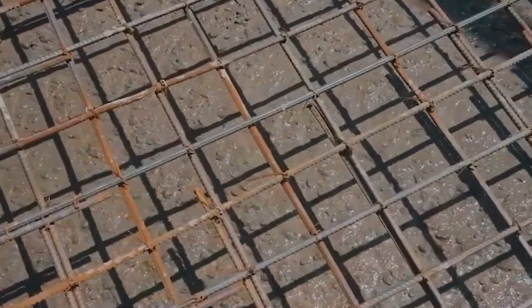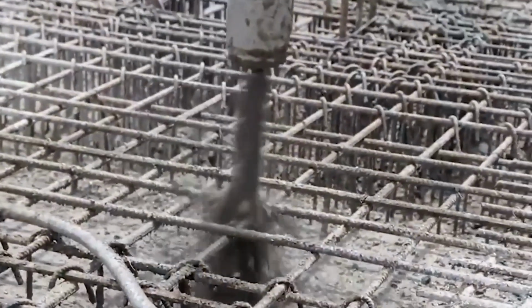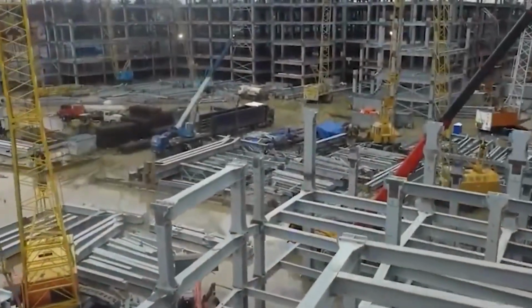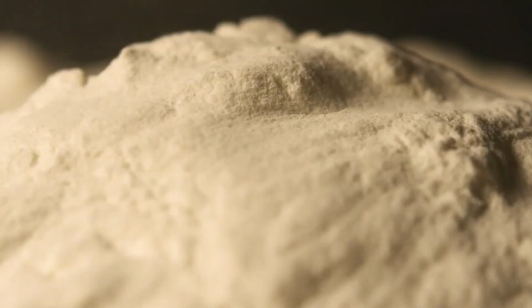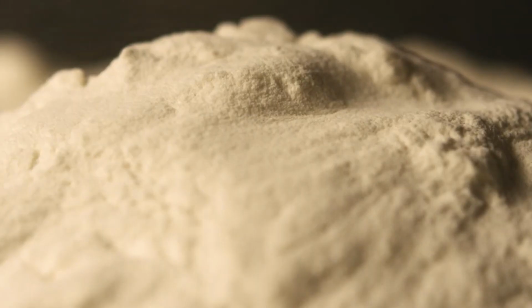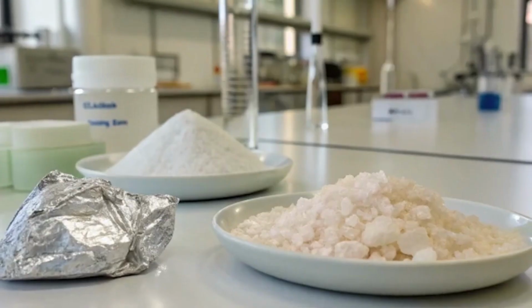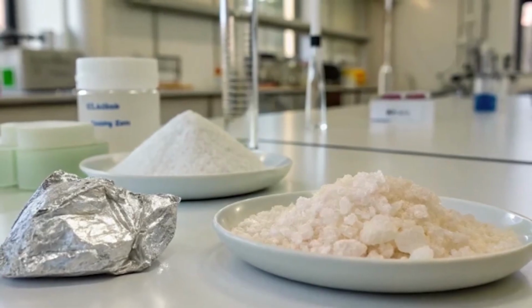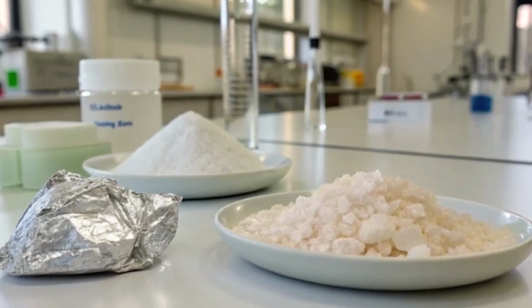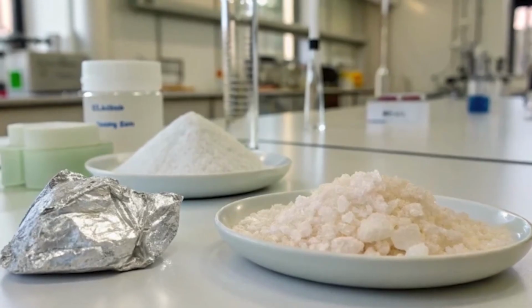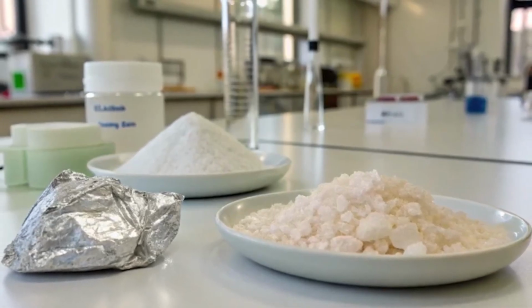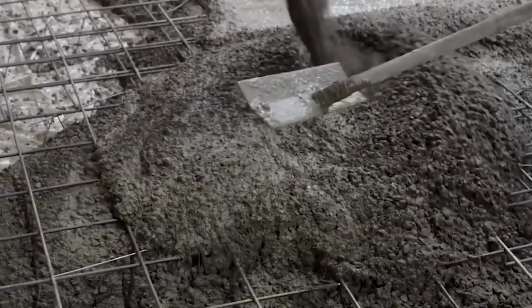Here is the brutal catch that slowed geopolymer concrete down for years after the chemistry itself was well understood. Ordinary Portland cement behaves almost identically batch after batch because its raw material, limestone, is processed into a standardized clinker before it ever reaches a job site. Fly ash and slag carry no such guarantee. Composition shifts depending on which coal was burned, which furnace produced the slag, and how the byproduct was collected and stored. Early geopolymer batches sometimes set within minutes, unusable for anything requiring a normal pour window. Other batches took far longer than expected, throwing off entire construction schedules.